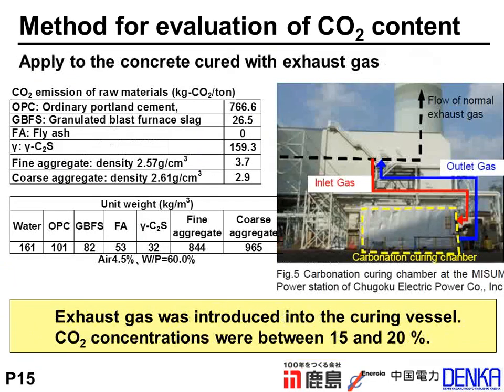So we apply this method to the concrete cured with exhaust gas. The carbon dioxide emission of raw materials and mixed proportion is below. We use blast furnace slag, fly ash, and gamma C2S, a low carbon dioxide emission substance, instead of Portland cement, and we manufacture the concrete specimen.